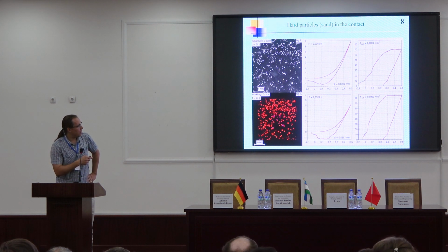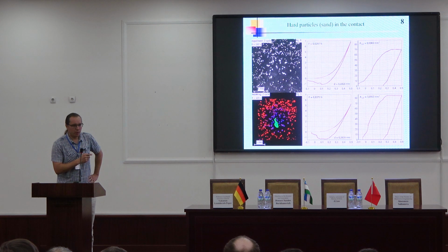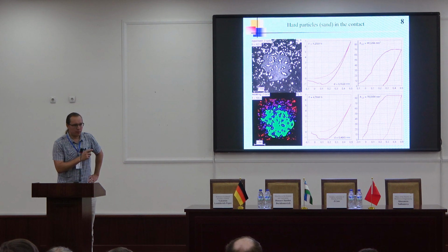And you can see here jump-like detachment of the rubber. It is always jump-like detachment, but if you have chemical non-homogeneities or particles or very big roughness, these sizes of rubber at this jump-like detachment are more pronounced.